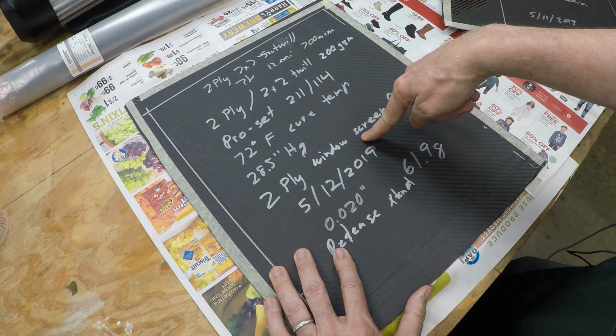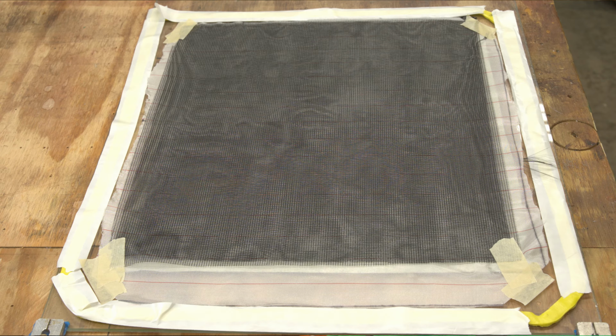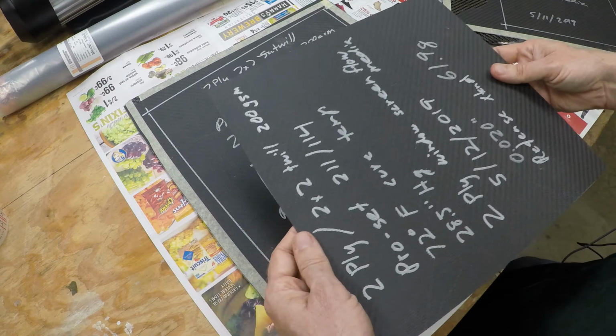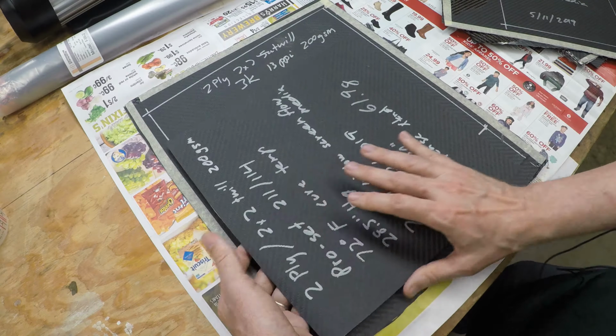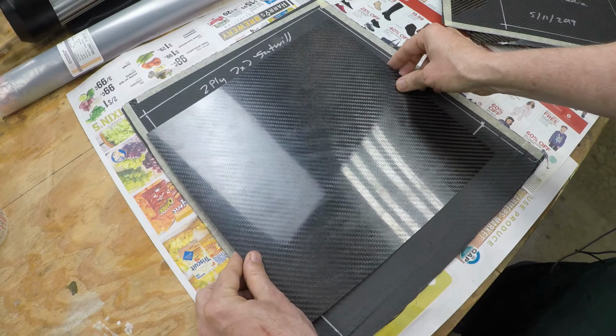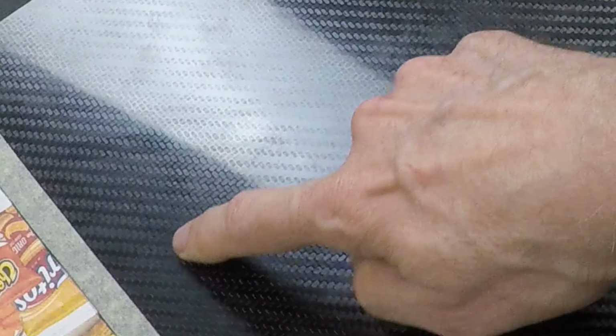So I thought, well, you know, if we put 2 plies of screen in there, it would be very difficult to plug up openings. The resin should be able to go in between those plies, up and down between the weaves of those plies. So that was the next test. So I put 2 plies in on the next test. And I got an excellent result. In fact, I've already trimmed this one. Resin went all the way through, and I got a fantastic finish throughout the part from end to end.